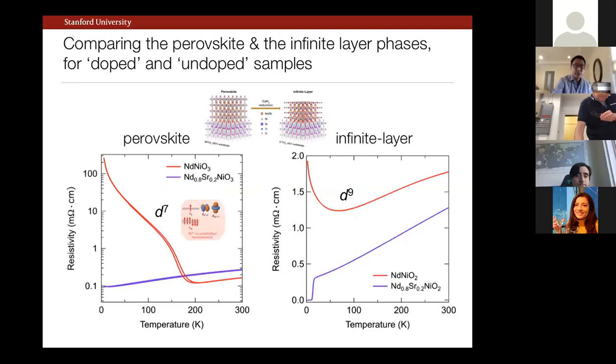So now if we look at the perovskite version of these thin films, here's neodymium nickelate. Again, it shows this characteristic large first order phase transition between a metal and an insulator. And I remind you, this is a d7 electron configuration. And again, as I had been fooling around with as a summer student so many years ago, if we dope, in this case nominally hole doping, we suppress this metal insulator transition.